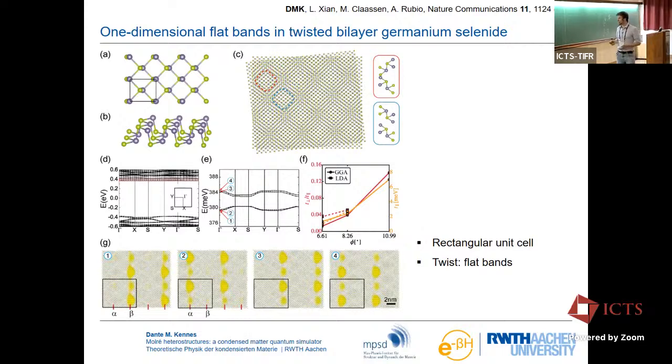So now we can push this through the electronic characterization, and we see a picture like this at 6 degrees. And you see, there's a flat band. It's a bit hard to see at this resolution, but we have a zoom in E. There's a flat band separating off this conduction band manifold up here. And as you go to smaller twist angle, this is actually getting flatter. So here in E, I have a zoom of this. It's just this red box being zoomed into. And this is a nice flat band, extremely flat, even at 6 degrees. But it also has another very peculiar feature.